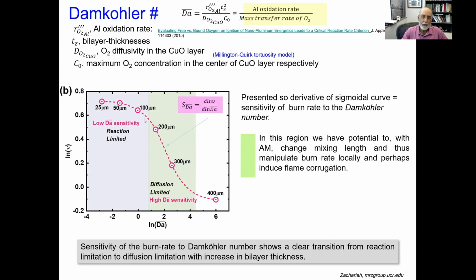in this green region where things are very sensitive, this is the diffusion limited region, but it's the region which is most sensitive. So this is the region where you can manipulate the process. There's not much you can do up here other than change chemistry. But over here, you can change architecture and you can change the nature in which you put things together for the corrugation or for whatever it is. And this is where the system will be most sensitive to the architecture that you present in the system, and therefore the ability to control burn rate, both in direction and magnitude.